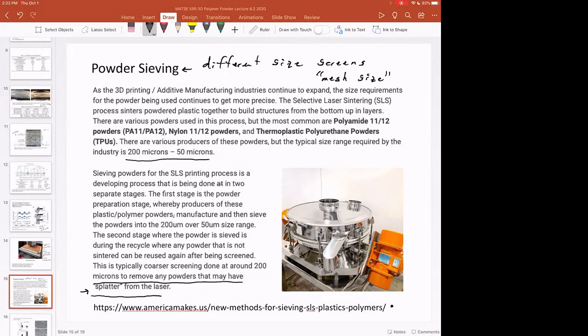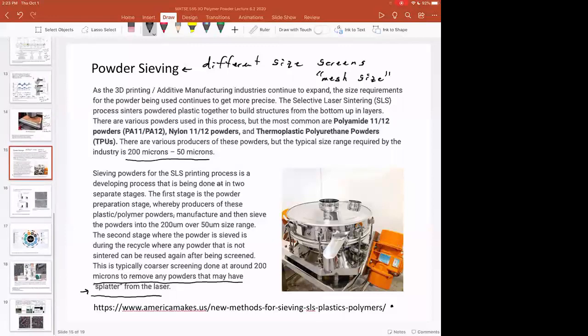And so the powder will age, the powder will slowly coalesce because you're heating it up to high temperature in the bed anyway. And so being able to reuse these powders, oftentimes they're sieved after they go through the SLS process in order to make sure the powder is all broken up and ready to go. So one of the important jobs of this sieving process is to get rid of any unusual shaped powder as it's passed through the instrument, because of course these larger particles will lead to spreading defects, streaking in the powder bed, other sorts of undesirable things. Any questions on that?